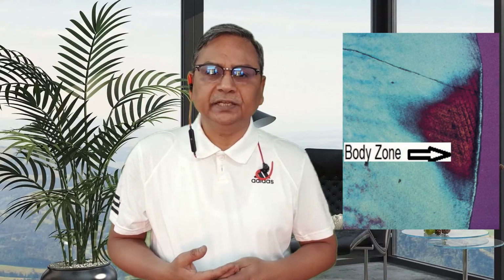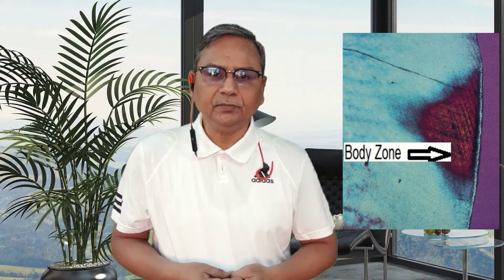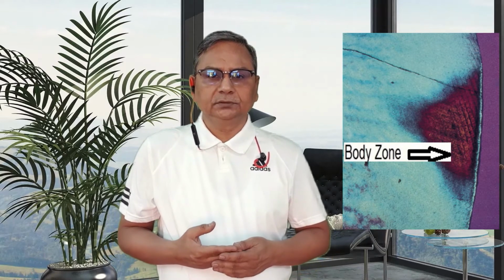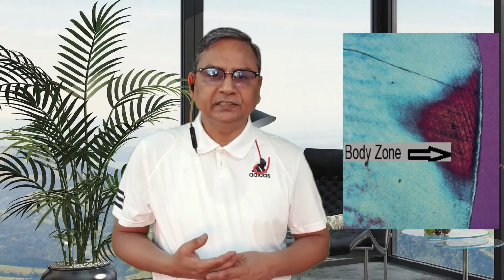This photograph also shows early enamel caries. The ground section is being viewed by polarized light after immersion in water. The body of the lesion and the intact surface layer is visible. The translucent and dark zones are not seen until the section is viewed immersed in quinoline.